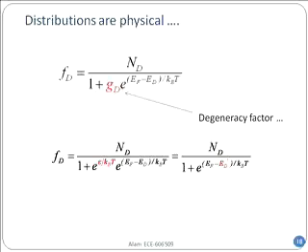Now, once you have set it up, all the calculations will come out right, because this is a physical property of the material and the donor. So as long as you have a silicon and phosphorus combination, you will have exactly one specific value for E sub D prime. Now, if you go to germanium and you talk about phosphorus, then you will have a slightly different value of ED prime. But in general, the ED value would have been different anyway, because of the different dielectric constant, because of the different effective masses. So why worry about it? We will just set it to a particular value and experimentally determine it. So that's what's called an effective donor level.